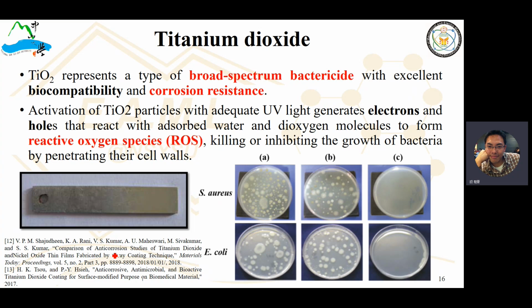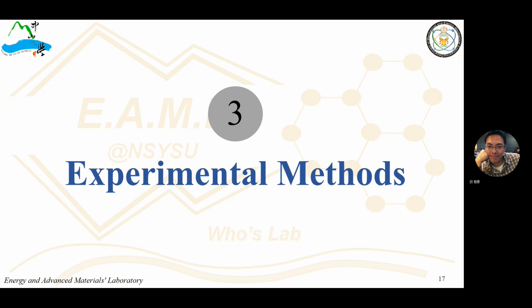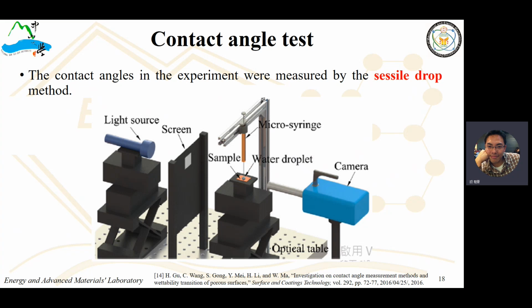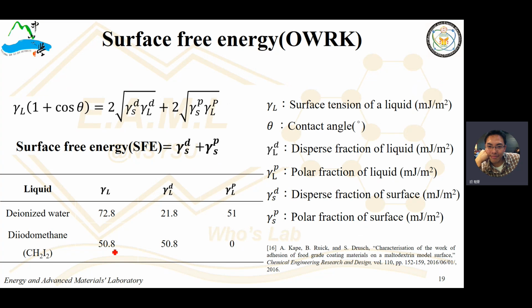Okay, and why I introduce this TiO2 is, I'm going to incorporate TiO2 with this polysilazane pre-ceramic precursor, and let's look at what its surface property is. Okay, there's an experiment. We measure the contact angle with the different surfaces of the polysilazane precursor incorporated with fluorine or diluted, or incorporated with titanium dioxide. And we calculate the surface energy by the OWRK method.